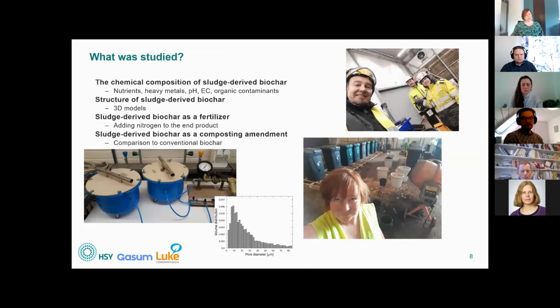And what we studied from them was the chemical composition. So what nutrients they had, if there was heavy metals, pH, electrical conductivity, organic contaminants. Then we wanted to look at the structure of sludge-derived biochar. As we know, wood-derived and other plant material biochar does have a sort of a very porous structure. And we were expecting this not to have as much porous structures, and we know that these structures are relevant when we use biochars in different applications. So we wanted to look into that to compare it to conventional biochars.